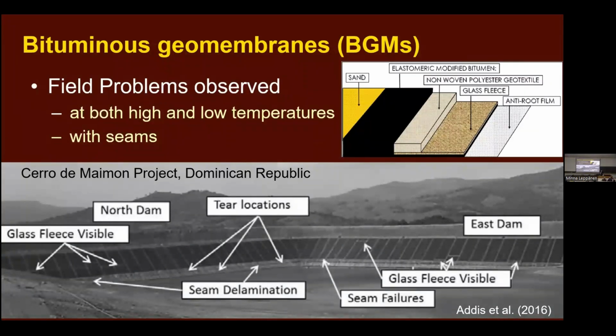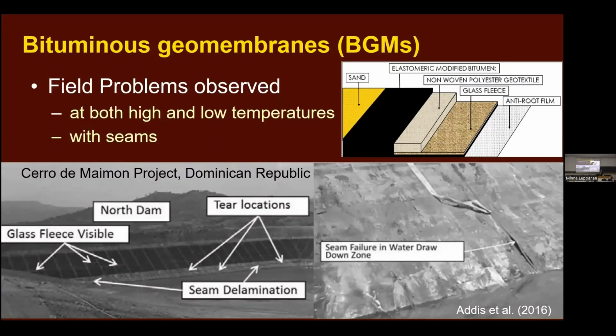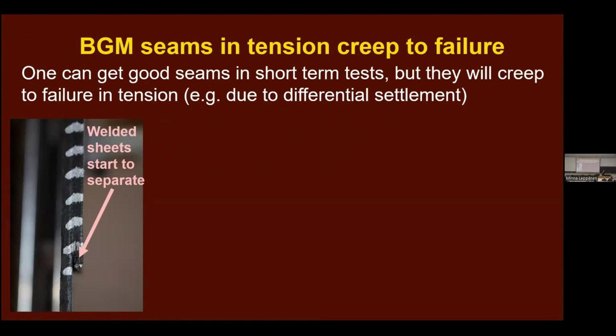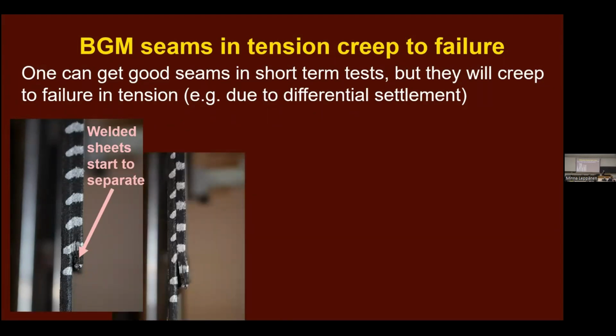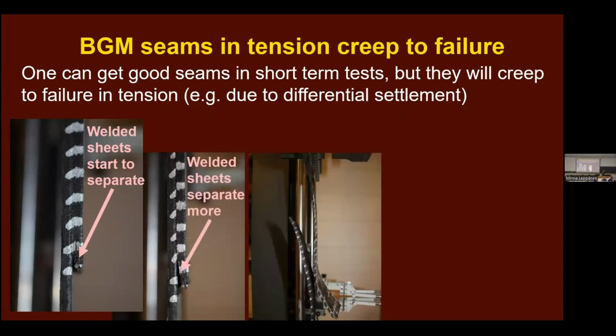These welds are having problems both at high and low temperatures, even in the sheet itself, but also in the seams. The problems have been highlighted. But I particularly want to talk about seams. So here's a test we did. We welded a sheet and then we subjected it to a sustained stress. Now, after the sheet was welded, we painted horizontal white lines on it. And you can see that those lines are no longer horizontal. Now they've actually separated, and you can see it's starting to delaminate at that location. And it's totally failed.